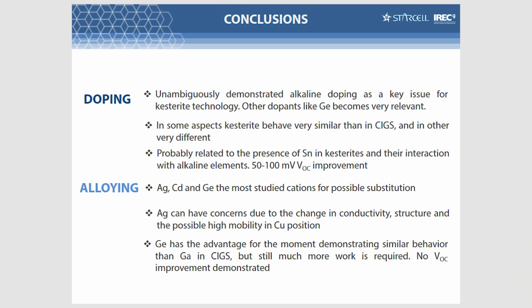In that sense, extrinsic doping has shown a very relevant effect on kesterite, and mainly alloying with this kind of silver and germanium compound can be very important in the future to really boost the efficiency of kesterite, and we are working a lot on that because we believe that this is the way to demonstrate efficiencies higher than 15% for this technology.